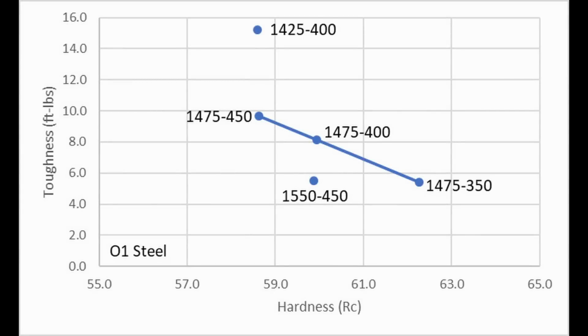Now, since we had excess carbon in solution with the 1084, the question is, could we have better toughness by using a lower austenitizing temperature to ensure we don't get too much carbon in solution? The answer to that is maybe. With O1 in the past, and I was mentioning O1 can end up with lower toughness because it has excess carbon in solution. I did an experiment where I austenitized lower than normal, 1425 Fahrenheit instead of 1475, and also compared with 1550. And using 1425 led to less carbon in solution and higher toughness. 1550, more carbon in solution and worse toughness.